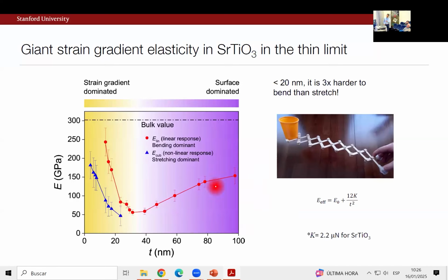So we found lots of structure in the way the Young's modulus varies as a function of thickness. So for reasons I don't personally totally understand, many materials have strong deviations from the bulk value on short length scales. Okay, so the fact that this is much softer, if you will, than bulk is maybe not such a shock. What's weird is I've never seen data for a single component system where you have this kind of abrupt non-monotonic behavior. So the point is, in red is the Young's modulus extracted from linear response. Again, this is dominated by bending deformations. And then just when we are thin, we can experimentally access a separate probe of the cubic nonlinearity. And we see a different Young's modulus apparently between the two. Okay? And this is sizable. It's about a factor of 3.